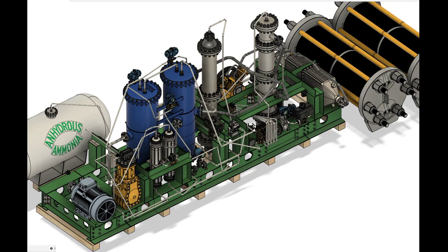Embrittlement will usually begin at the site of a crack, notch, or corner, or in any site with high multiaxial stress. Because these sites have high inter-atomic distance, they are conducive to hydrogen penetration. The hydrogen begins to permeate, and enlarges these sites until they reach their critical fracture stress.